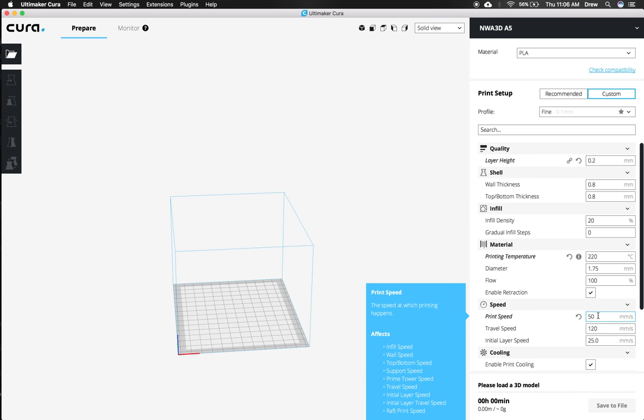because we want to make sure that it doesn't go faster than 50 millimeters a second, because if it does, the layers might not stick together and it'll cause more problems. And that's with any 3D printer. Even though this 3D printer can print a lot faster than that, we always recommend printing at a max speed of 50. And the travel speed, we'll go ahead and leave that the same, but this initial layer speed, we're